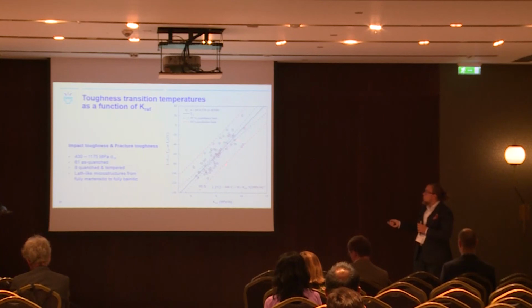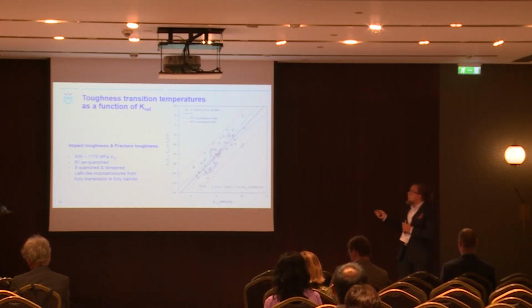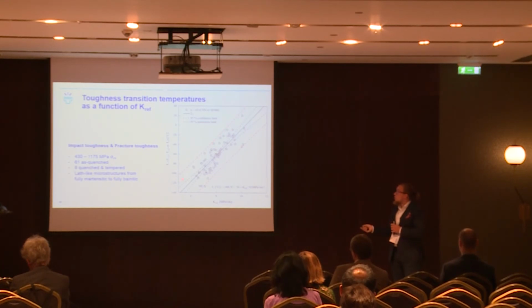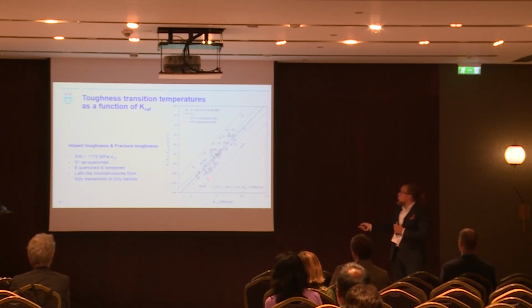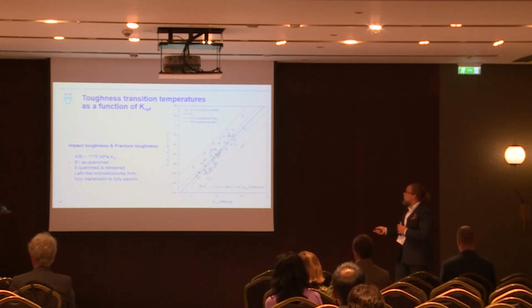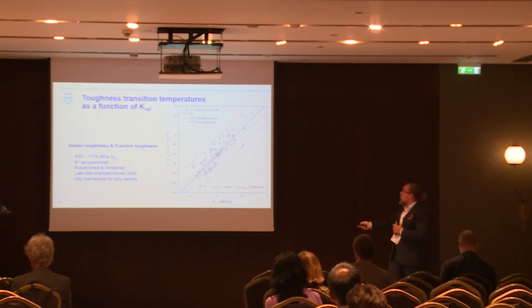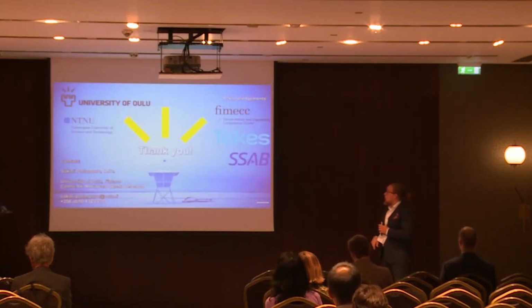So this is the main result of this, incorporating 69 different materials from impact toughness tests and fracture toughness tests. We get this trend for the propagation that has a standard deviation of 18 degrees, but we have also a very wide range of yield strengths from 400 to 1200 megapascals, and they have also both air-quenched steel and quenched and tempered steel materials with varying phase constituents. And with that, I want to thank you.